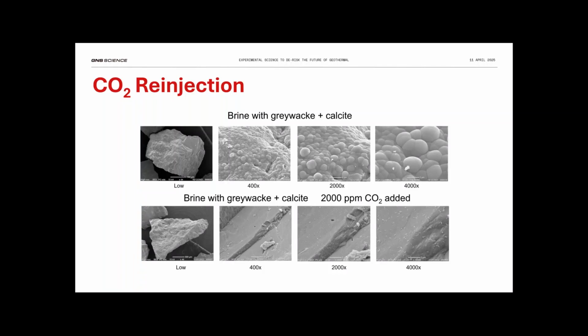How does that work? It's because CO2 is a pH buffer. So when you add CO2 to the brine, you're forming carbonic acid. So every time an H+ is consumed by the calcite, the carbonic acid molecule dissociates to form H+ and bicarbonate. So it's acting as a pH buffer. And so instead of the pH going from 4.5 to 8, the pH goes from 4.5 to 5.5. And the CO2, the carbonic acid, keeps the pH buffered. And so you have no polymerization of silica. So the fluid can pass the formation, even though there's calcite present, without the pH actually being neutralized.